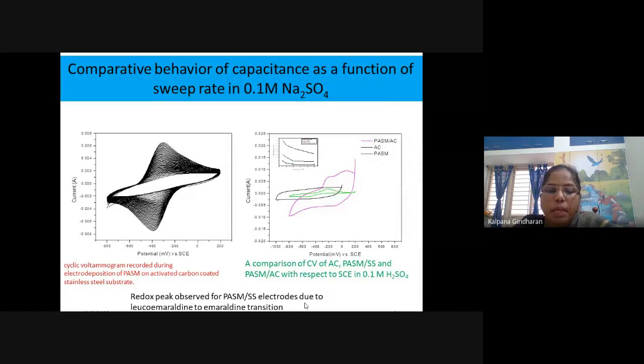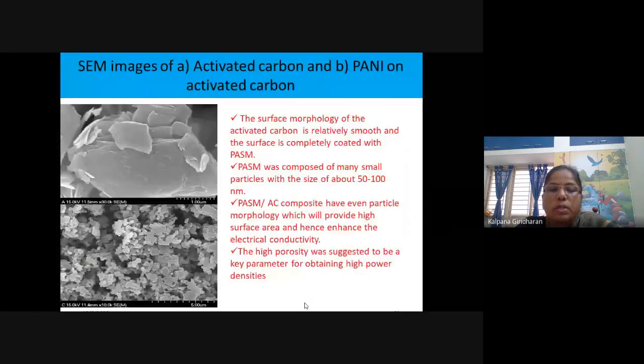This peak, obtained during electrodeposition, is this redox peak, due to the leucoemeraldine to emeraldine transition. This is the surface morphology.